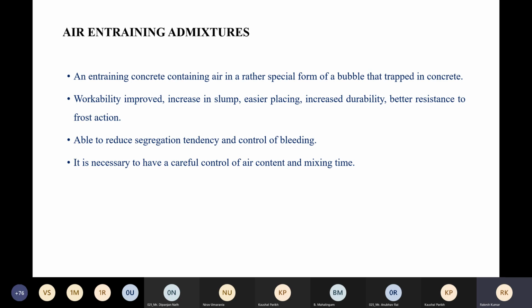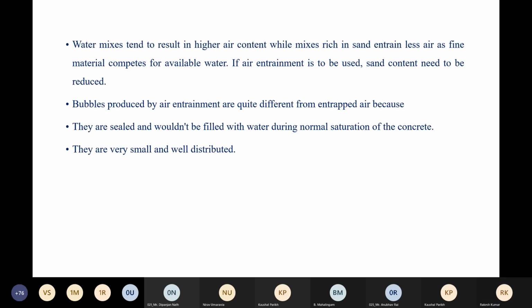So it is necessary to have careful control of air content and mixing time. So when we use the chemical admixtures, we must be very careful. Wet mixes tend to result in higher air content, while mixes rich in sand give less air, because the fine material content is more. If an air entrainer is to be used, sand content needs to be reduced. Once you are using the fine aggregate, in that case there will be less free space for the placing of the air in the voids.